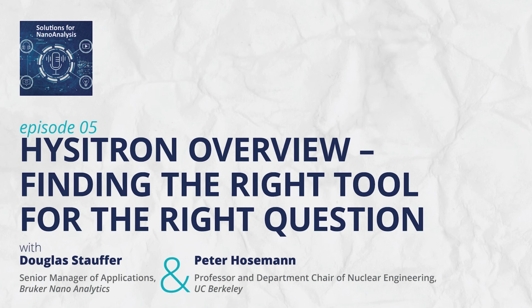Yeah. But it provides the statistics, right? Absolutely. That's a huge advantage of it, right? Yeah, going back to that weld example, if you look at something very simple like the Tabor relationship, right? Hardness is 3 times your yield strength. It's really defined by this constraint factor, but in a weld, that constraint factor changes depending on the material. Intermetallics don't have a constraint factor. So hardness is a little bit more abstract than, say, the yield strength, right? With yield strength, the ASTM guidelines are very clear on how it's calculated.